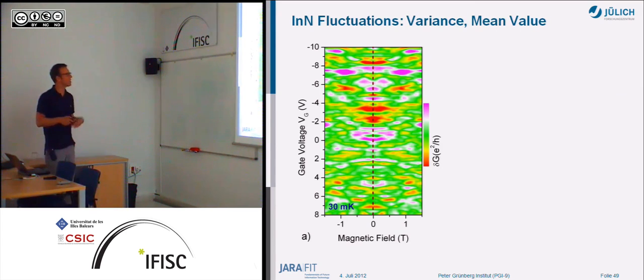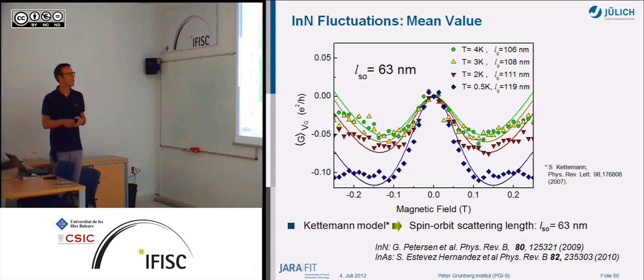And this is shown here just as an example. If you look from the top now, this is the pattern of the conductance, so it's fluctuating at zero magnetic field, and what you're doing is you take an average and just average everything, and then you see you get a smooth curve as a function of magnetic field, and then you see a peak here in the conductance. Yeah, this conductance here you can look in more detail. We have nicer measurements here, but here you can get information about spin-orbit coupling by looking at this peak here, which is due to weak anti-localization. Yeah, this is a typical curve.